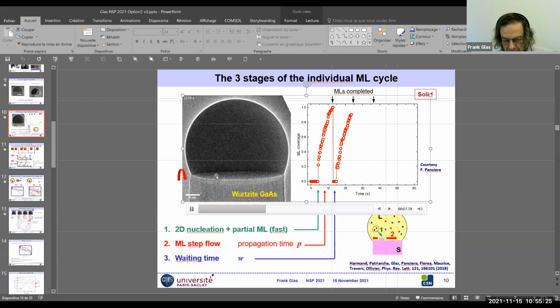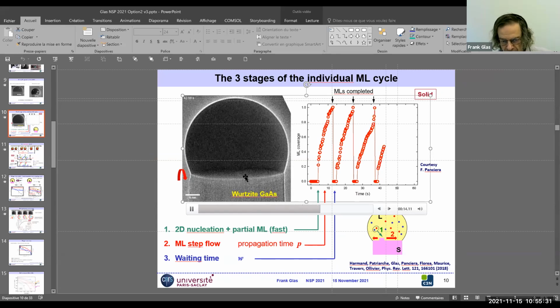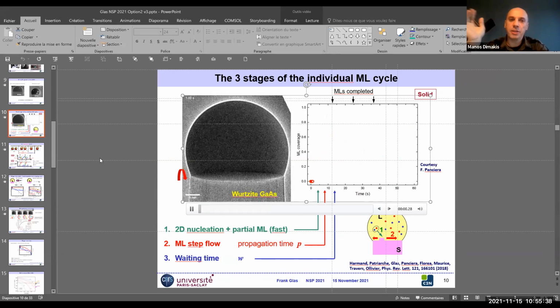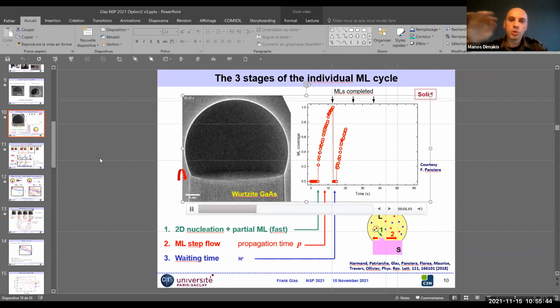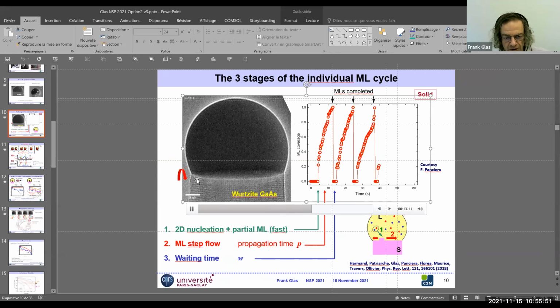It's more complicated because we don't have experimental data at the moment. We don't see the propagation. And because the situation is more complicated, because the monolayer is fed by the liquid and by the solid. But the question is still the amount of atoms that you will get from the truncated planes. Will this be enough to complete the monolayer, or is it a self-regulating process? That's probably a question which is open.